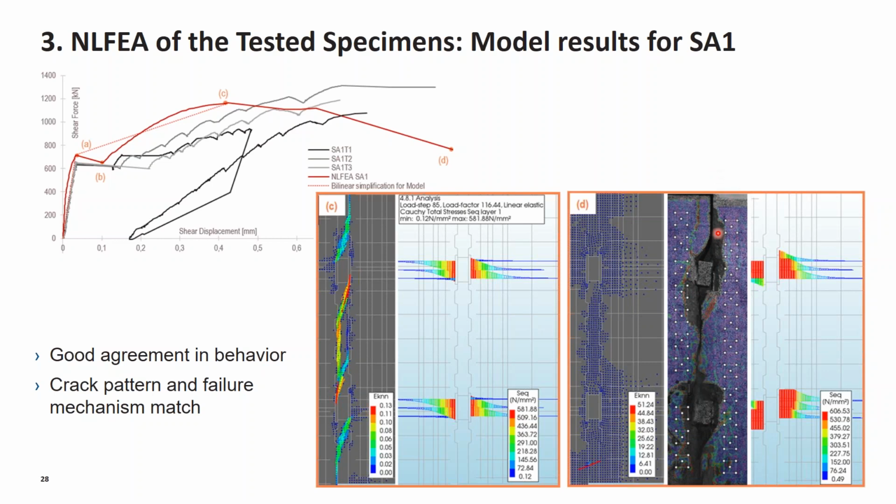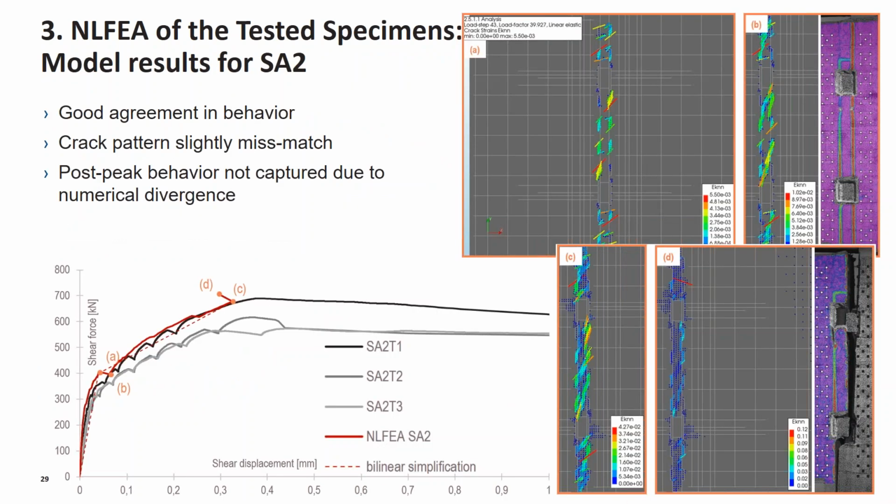We have an explosive failure followed by the two elements separation, and this behavior was not captured with a smeared cracking approach. We encountered the strain localization after the reaching of the peak load, and the same behavior can be observed for the second test series.